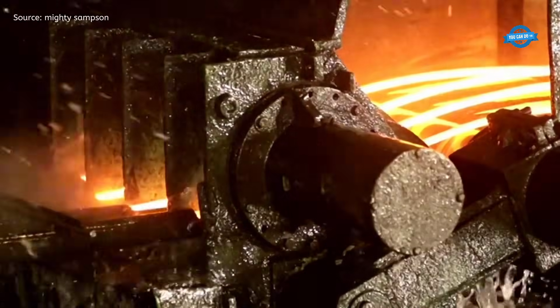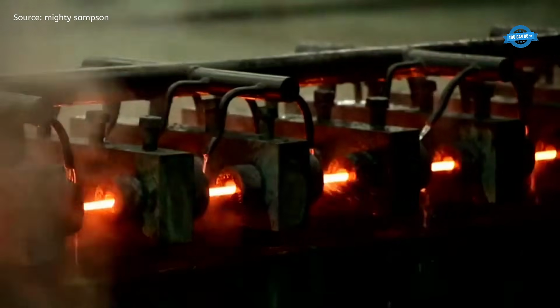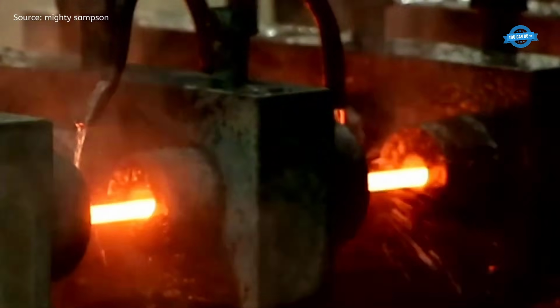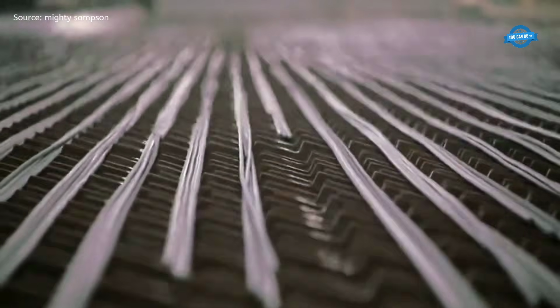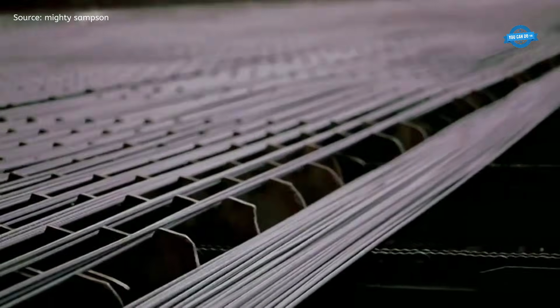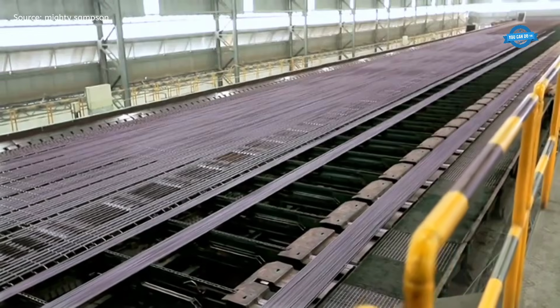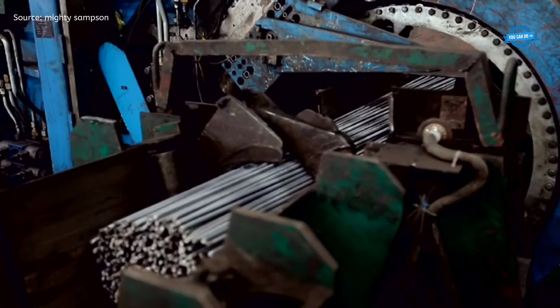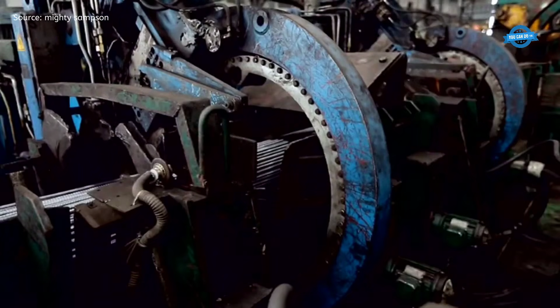After rolling, the steel bars undergo thermomechanical treatment, TMT. This involves rapid cooling of the outer surface while keeping the core hot. This temperature difference forms a tough outer layer and a ductile inner core, resulting in TMT steel bars. The bars are then cooled on a 12-meter-long cooling bed, the largest in Bangladesh, before being cut and bundled.